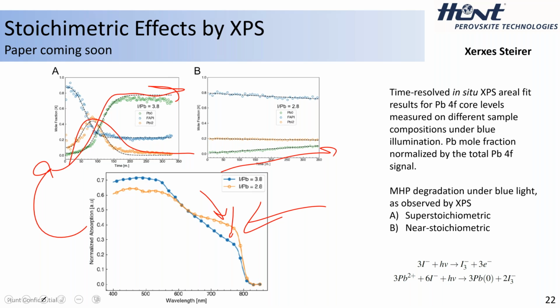But what we believe is happening is that since this is photo aggregated, we have some sort of photo-mediated reaction where you have 3 iodides plus light can make a triiodide molecule plus 3 electrons. Those electrons can then react with the lead to reduce it to form 3 moles of lead for every 6 moles of iodide consumed. So not only does this consume the iodide material, which is bad, right? So as we described before, you cannot lose your FA or your I.